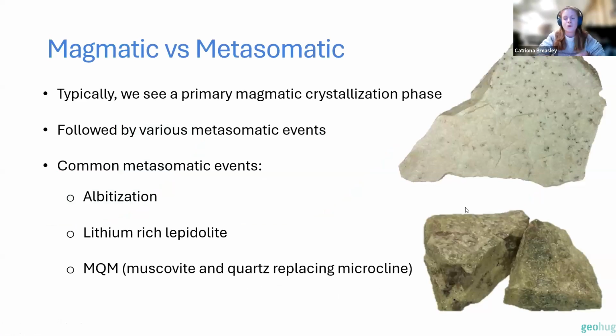So usually two major processes occur in pegmatite paragenesis. So typically we see this first stage of primary magmatic crystallization where you get these blocky crystals, you can get apatite, which are then followed by various metasomatic events. So I've put three really common metasomatic events in lithium-bearing pegmatites on the screen here. You can have albitization, which is a sodium-enriched event, which acts to usually replace blocky primary K feldspars. Then typically later in the metasomatic sequence, you can get more lithium-enriched metasomatic events, and these can precipitate lepidolite. And also you can get MQM alteration or muscovite and quartz replacing microclines.